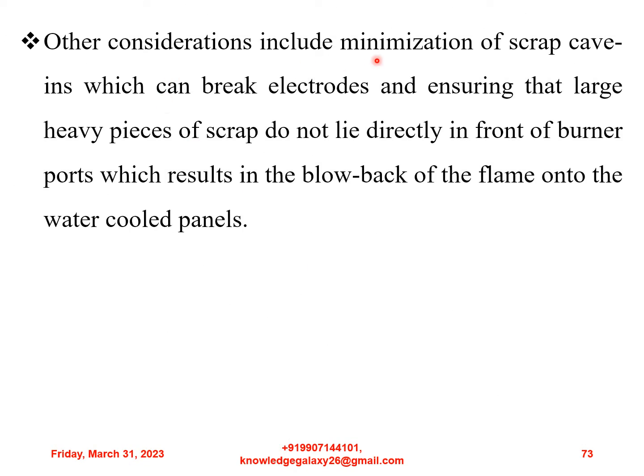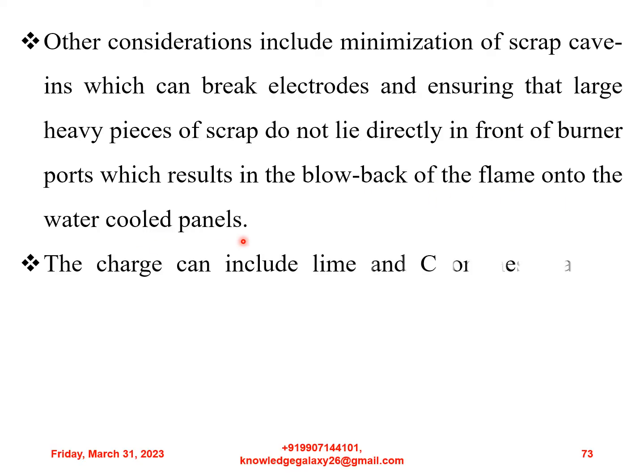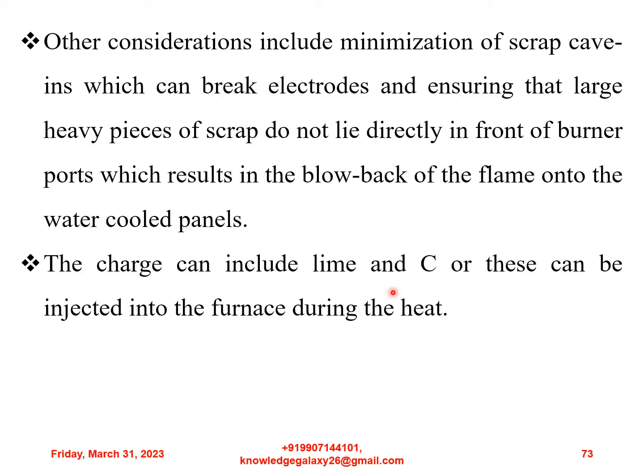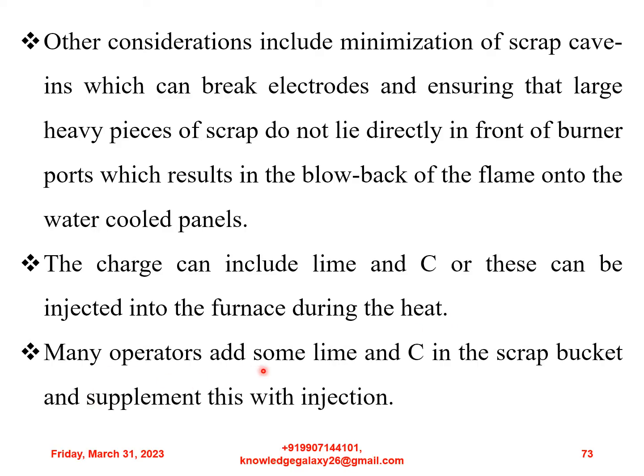Other considerations include minimization of scrap cave-ins which can break electrodes and ensuring that large heavy pieces of scrap do not lie directly in front of burner ports, which results in the blowback of the flame onto the water-cooled panels. The charge can include lime and carbon or these can be injected into the furnace during the heat. Many operators add some lime and carbon in the scrap bucket and supplement this with injection.